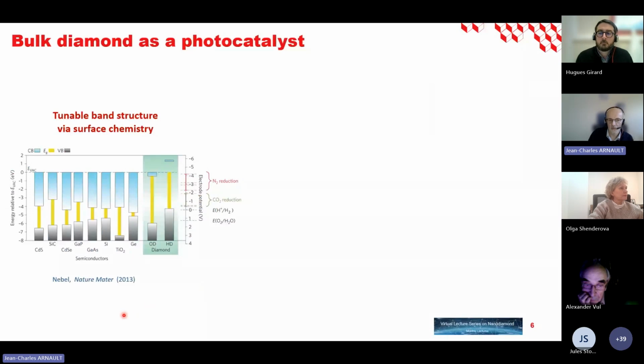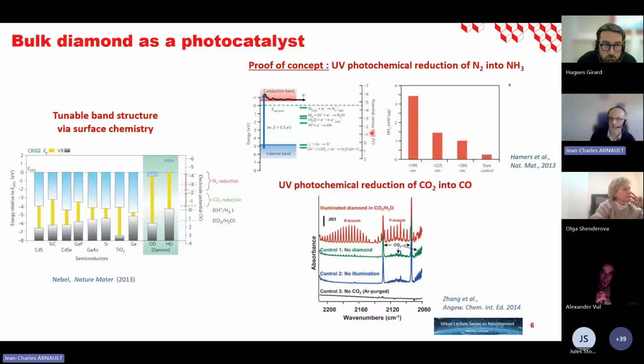This is a specific semiconductor in the sense that the band structure is very sensitive to the surface chemistry. And you know, probably, all this work showing that when the surface is hydrogenated, you get a shift of the whole band structure by 1.5 electron volts. So in that case, if you illuminate in the deep UV and promote electrons in the conduction band, these electrons will be very strong reductants. And Hamers' group showed that these electrons, the solvated electrons, can be used to reduce nitrogen or even CO2.